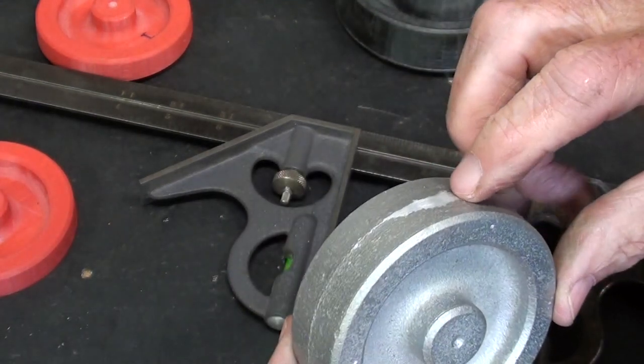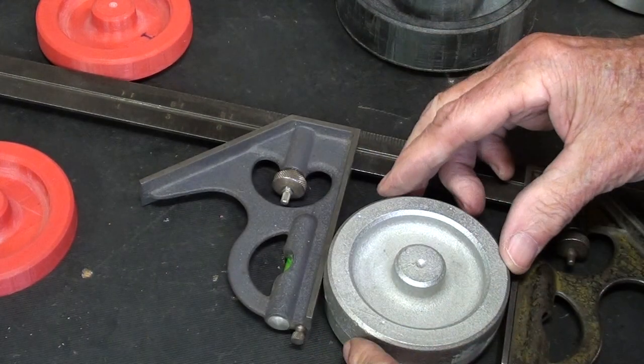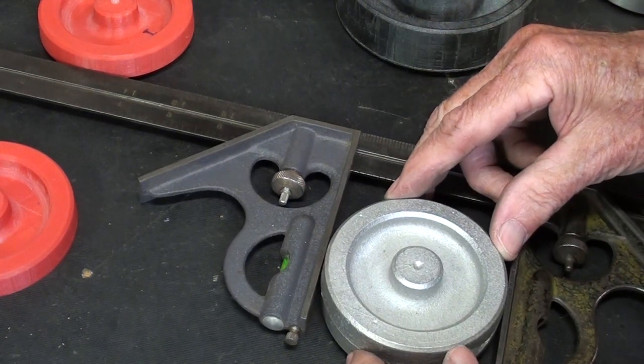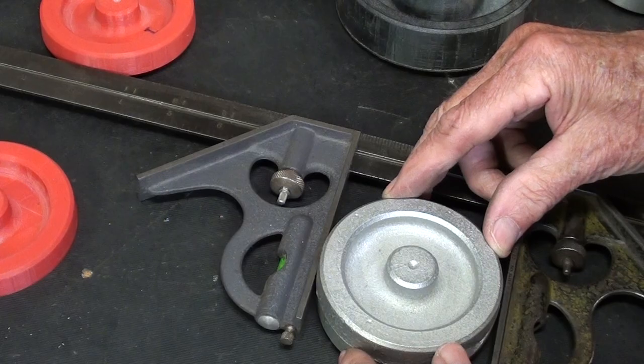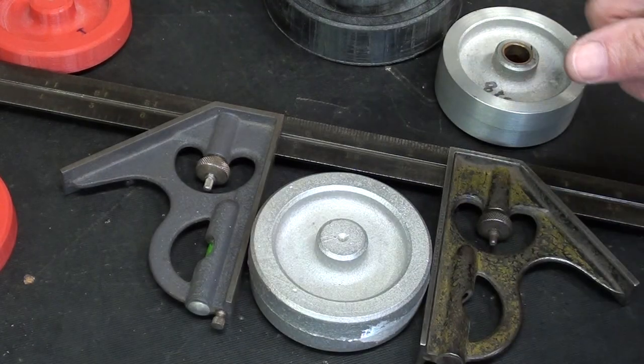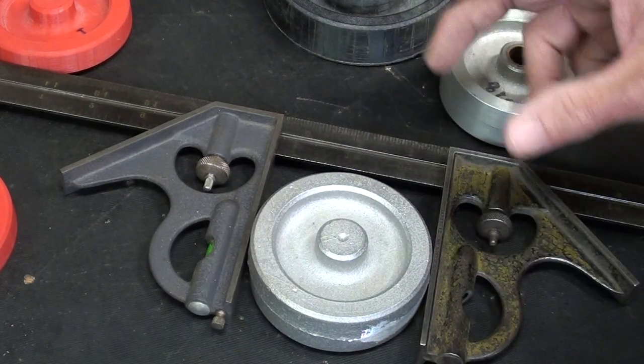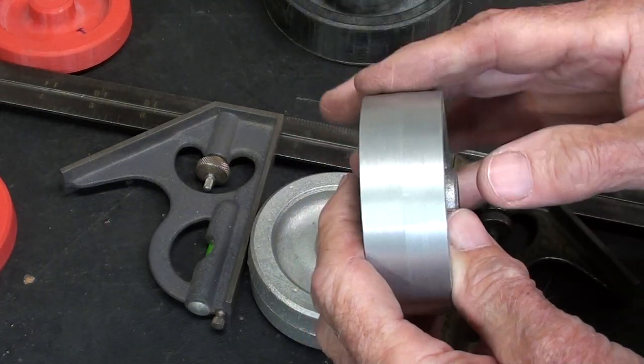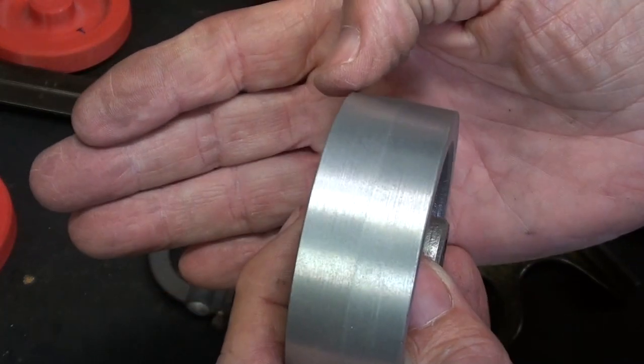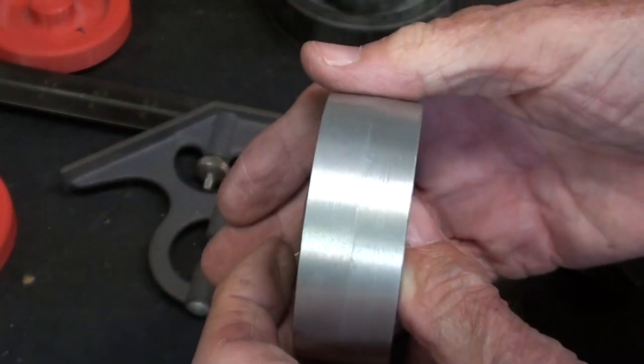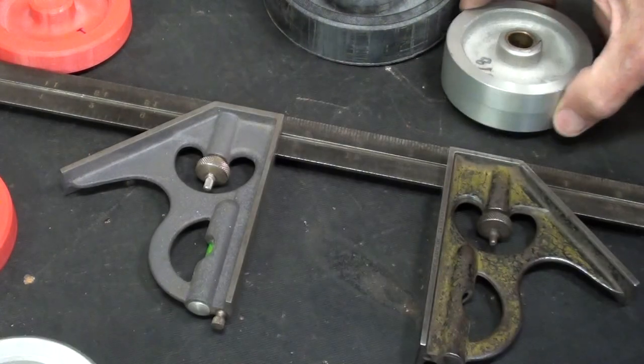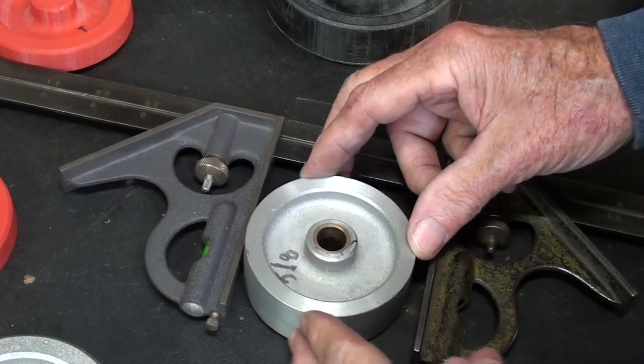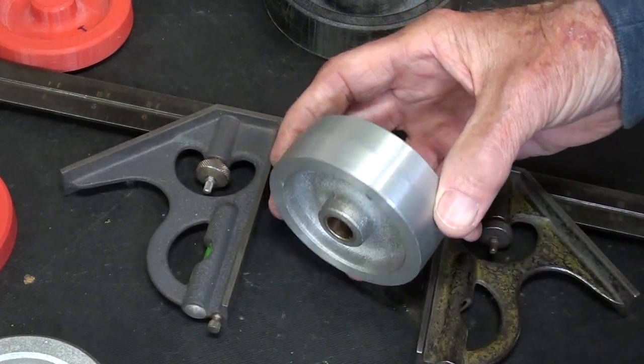And here is the casting, and I just took this to the sander and knocked off the flashing there, but the difference will not be as dramatic, because it's a smaller casting. But you can see that it is a different size. And let's see how much machining allowance that I had on this, so that it ended up being 3 inches or thereabouts. Because not only was this turned to diameter, it is also turned with a taper or a crown on it to allow the belt to track. So you can see that there was quite a bit of material allowed for machining.